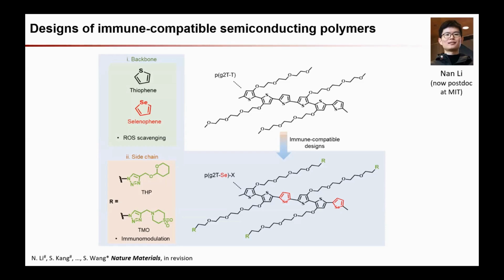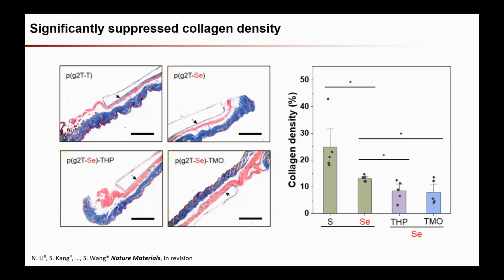And then we also took a look at the sidechain structure, by directly grafting some immunomodulatory groups at the end of the sidechain, with a hypothesis that they could provide similar effects for the immune compatible functions. After synthesizing this polymer, again by my student Nan, we implanted it in mice through subcutaneous implantation, and after 4 months took it out and did the tissue analysis surrounding the implant.